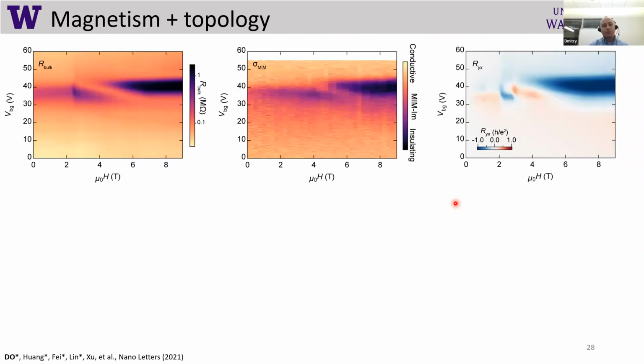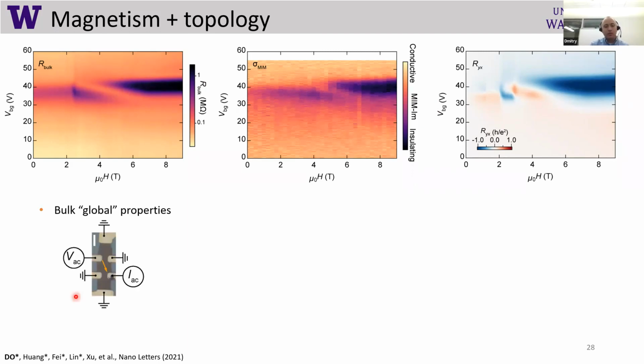So after that is done, we can now have a look at how magnetism and topology interact. For that purpose, we did measurements of different things, and there are 3 maps shown here, and each of them informs us on a certain aspect. So the left one is the global conductivity of the sample, and the way we do it, we have a special device geometry which allows us to avoid edge states. So we measure only the bulk of the system.